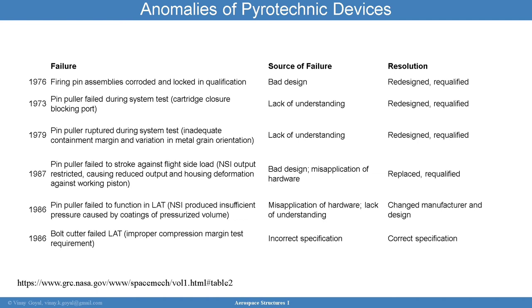In 1979, the pin puller ruptured during a system test, and there was inadequate containment margin and variation in the metal grain orientation. So grain orientation can be a significant issue. There was also a lack of understanding, and the resolution was to properly redesign and requalify the system. In 1987, we have the pin puller which failed to stroke in flight, and you had a side load there. The NSI output was restricted, causing reduced output and housing deformation against the working piston. So a bad design means misapplication of hardware here. They had to replace and requalify. That was the bottom line.